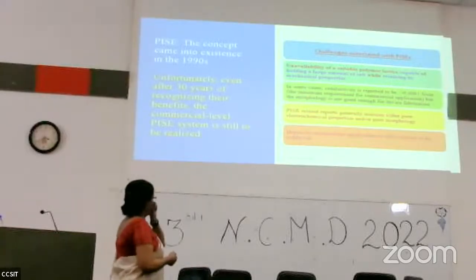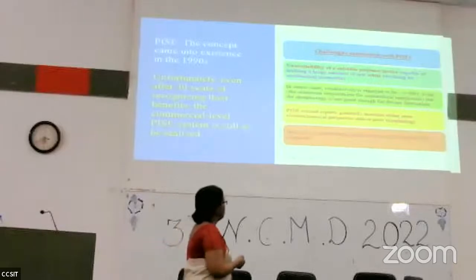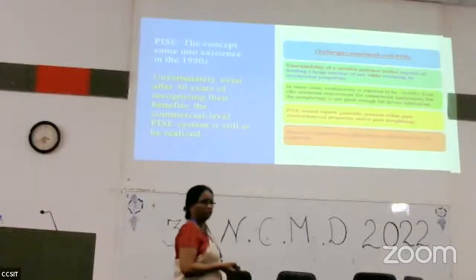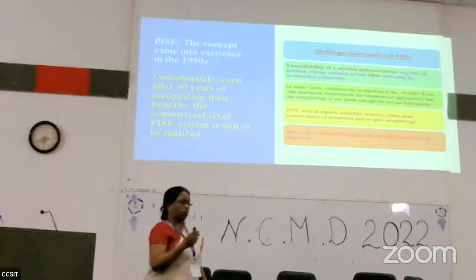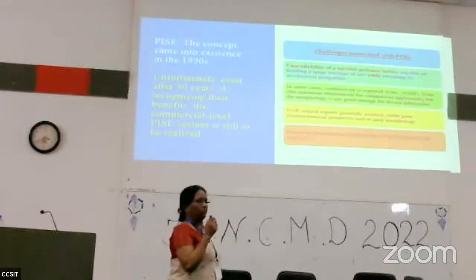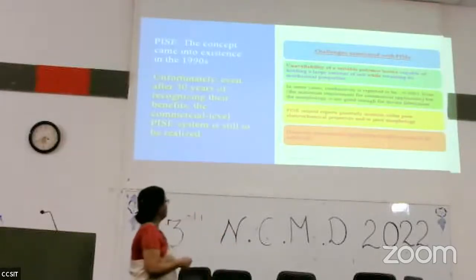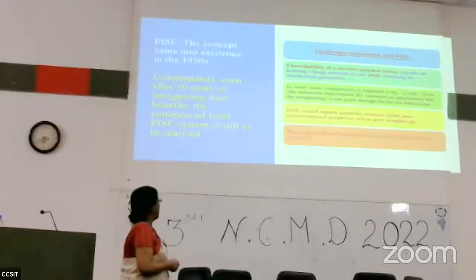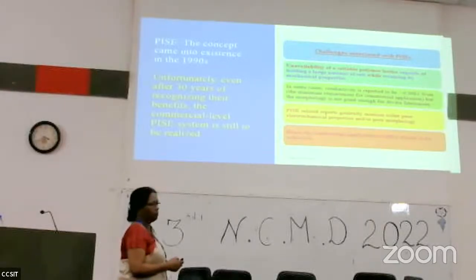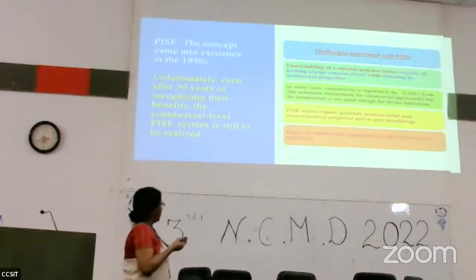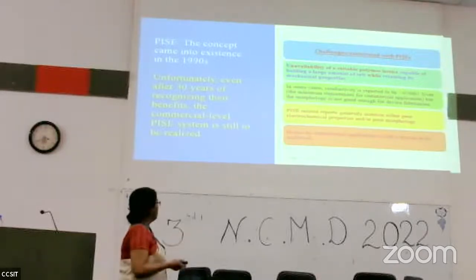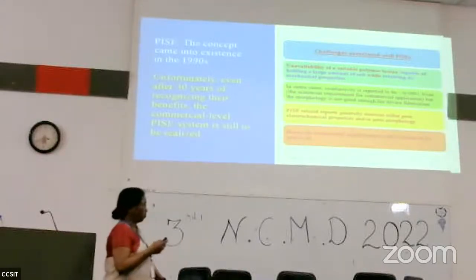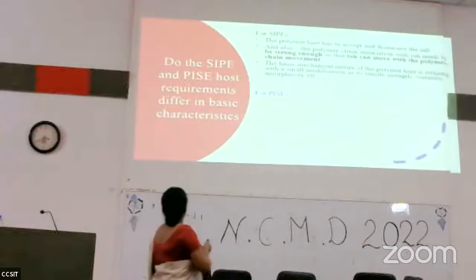In some cases, conductivity is reported of the order of 10 to the minus 4 to minus 5. But in that case also, the mechanical quality of this is not good, and both are there. That is also not very good. Hence, the commercial application is yet to be achieved. All these samples are very promising.